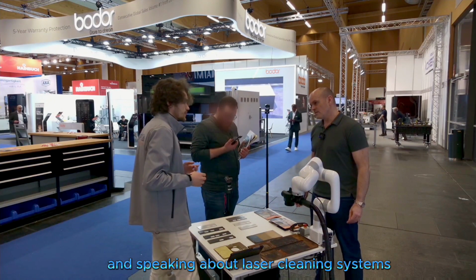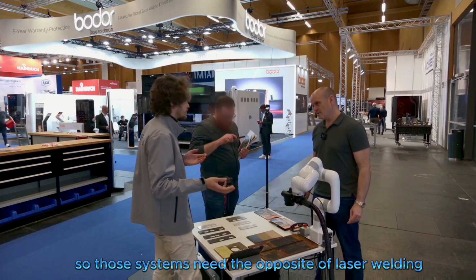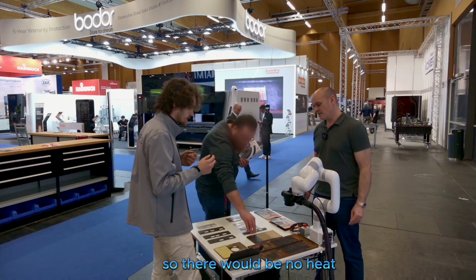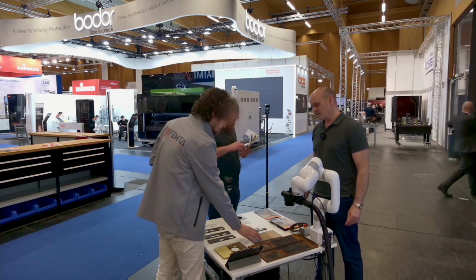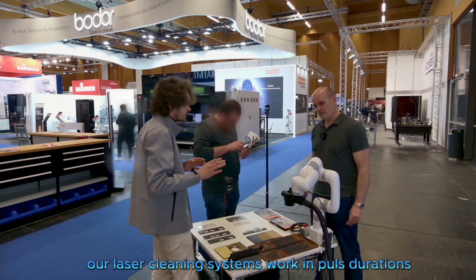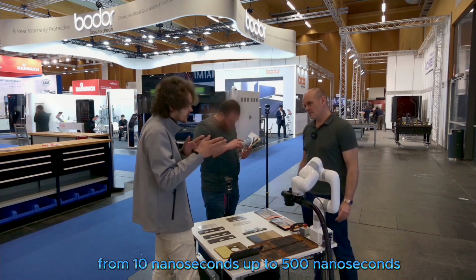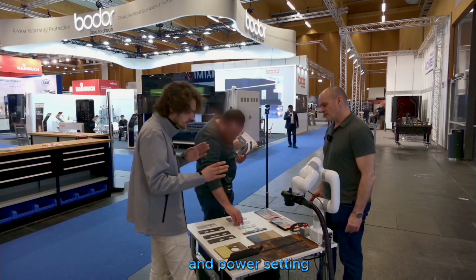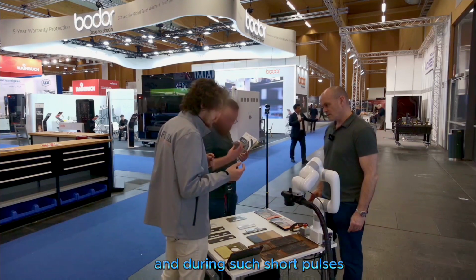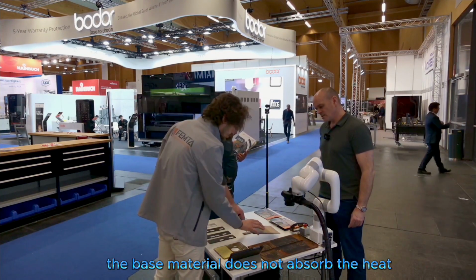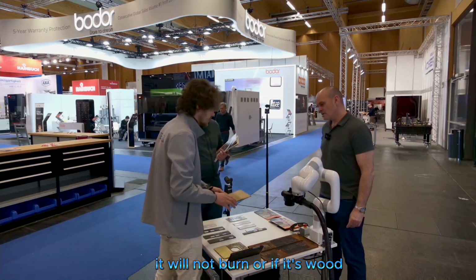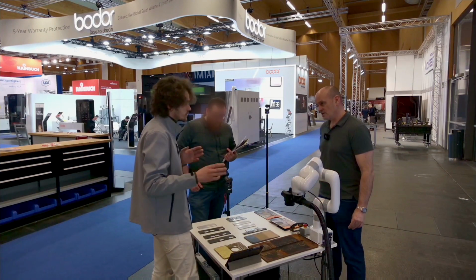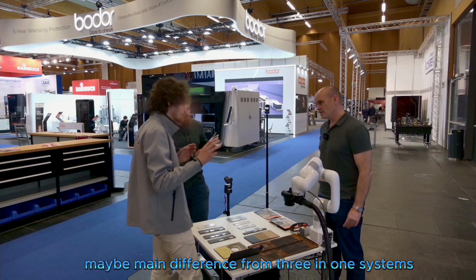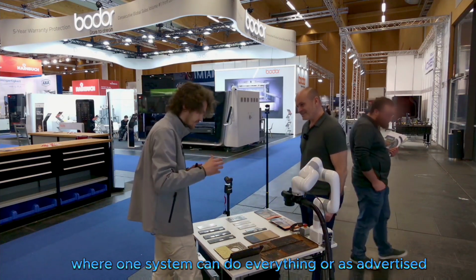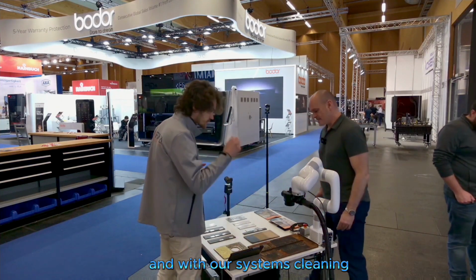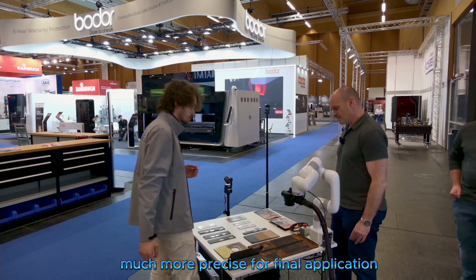And speaking about laser cleaning systems, those systems need the opposite of laser welding. They need really short pulses, so there is no heat transfer to the material that is being cleaned. Our laser cleaning systems work in pulse durations from 10 nanoseconds up to 500 nanoseconds. It can be adjusted, and it also depends on repetition rate and power setting. On average, it's in the 100 nanosecond range. During such short pulses, the base material does not absorb the heat. So, for example, if it's cardboard, it will not burn, and if it's wood, it will also not be damaged. This is maybe the main difference from 3-in-1 systems, where one system can do everything, as advertised, but they cannot, for example, clean sensitive materials. With our systems, cleaning is much more sensitive and much more precise for the final application.